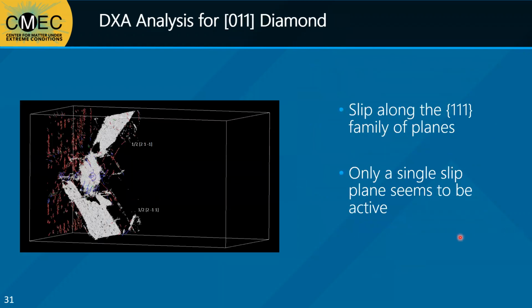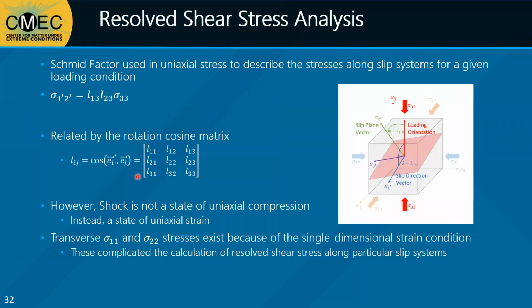In our DXA analysis of the 011 case, we can see that the stacking faults are instead occurring along the 211 direction in the 111 family of planes, with no sign of activity in the 100 family of planes. Additionally, only one slip plane seems to be active, symmetric across the void. To help explain the presence of these dislocations, we turn to a resolved shear stress analysis along the active slip planes of our diamond cubic system.